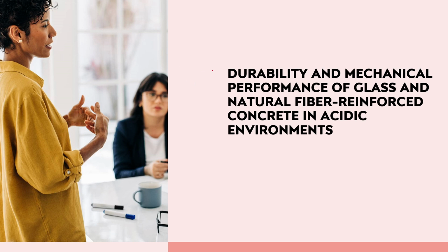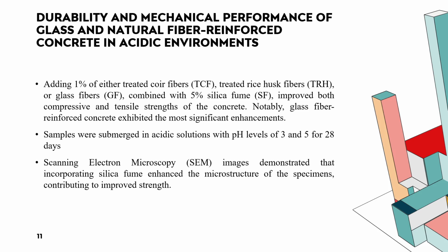Next is durability and mechanical performance of glass and natural fiber reinforced concrete in acidic environment. There is glass fiber and there are natural fibers, and they have tested in acidic environment. In this paper they added 1% treated coir fibers, rice husk fiber or glass fiber, and combined this with 5% silica fume. They found improved compressive and tensile strength of the concrete. Notably, glass fiber reinforced concrete exhibited the most significant enhancement.